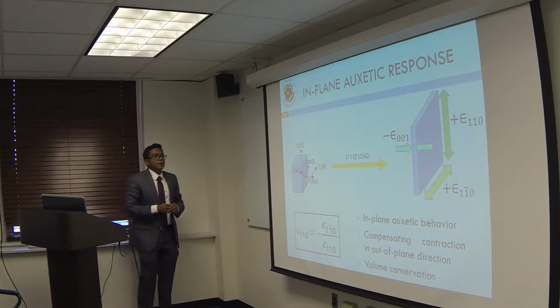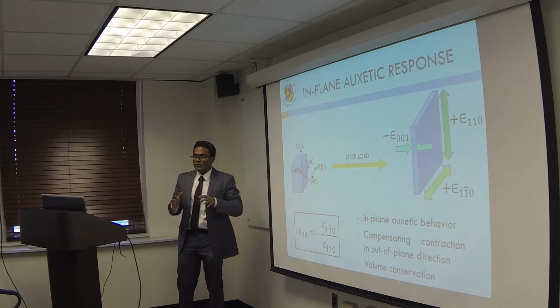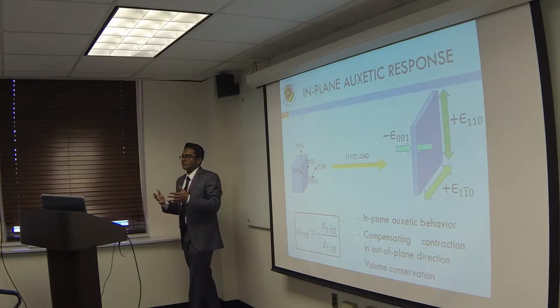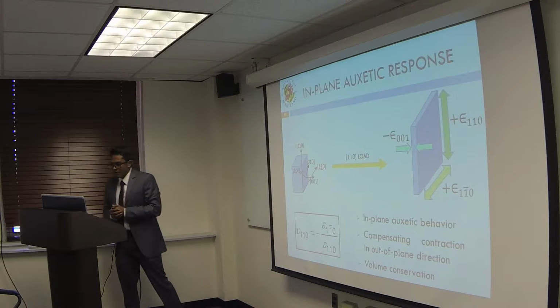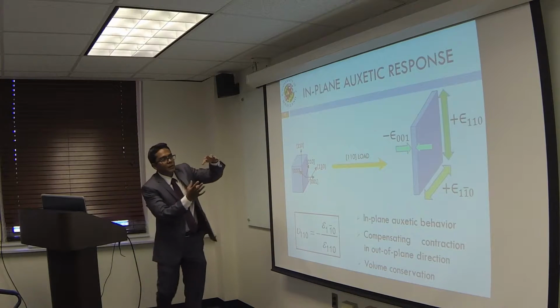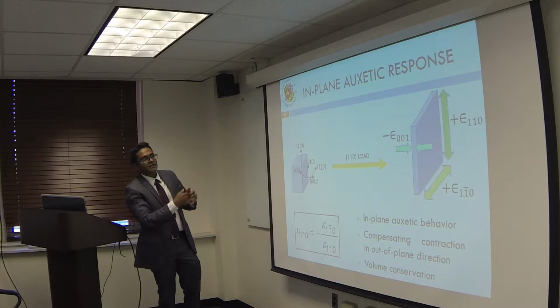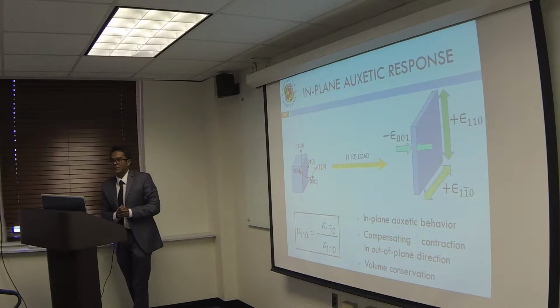Another interesting aspect here is that this response is volume conserving, so there's a contraction in the third, out-of-plane direction. So when the 110 dimensions increase, there is a decrease in the dimension of the 001 direction.